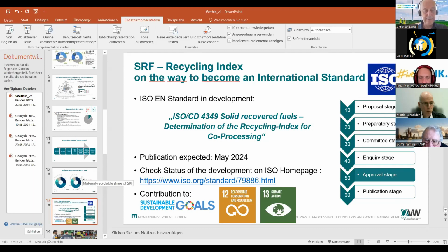And the standard says also that you have 2 possibilities. You can do 4 oxides or 9 oxides, depending on how much you want to analyze. And we believe that this could bring additional advantages for the recycling industry, because we are bringing recycling to materials which are not recyclable now. So the target of co-processing is not to burn waste which is recyclable, but we believe that we can bring additional recycling quotas for different industries.